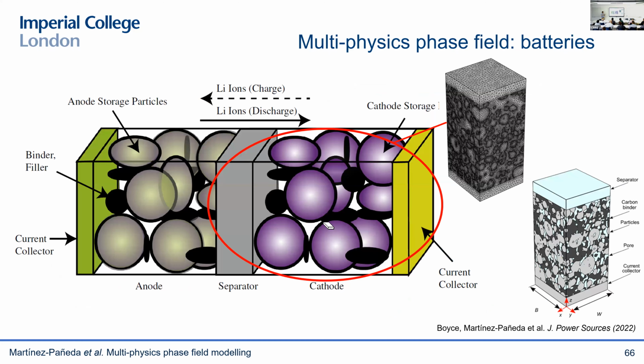And we have taken this one step further. This is together with colleagues at UCL who are very good in imaging facilities. They have this very nice X-ray imaging facility. So we are able to model not only the particles, but the entire electrode. We're able to capture the effect of the pores, of carbon binder, of the current collector, of the electrode thickness. So all these other secondary phases that also play a role.